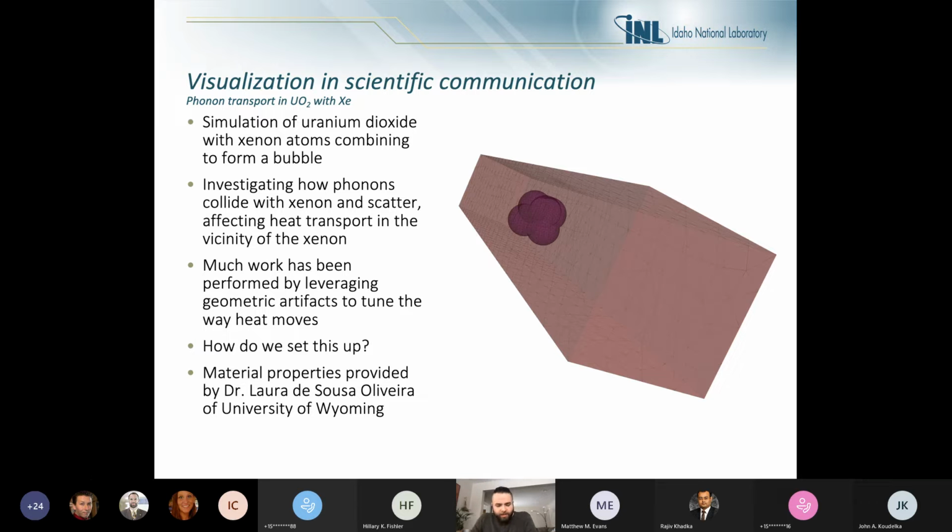To give a plain example, a reactor cycle is one fuel cycle where we run a nuclear reactor for 18 to 24 months on a certain set of fuel, and as this fuel is fissioned, its uranium content goes down and its defect content goes up. The things that you think about as nuclear waste aren't really nuclear waste. They're spent fuel, and they're actually really useful for the future, but that's another topic. Xenon forms in UO2 through fission, and xenon affects reactor control heavily and also reduces thermal conductivity.